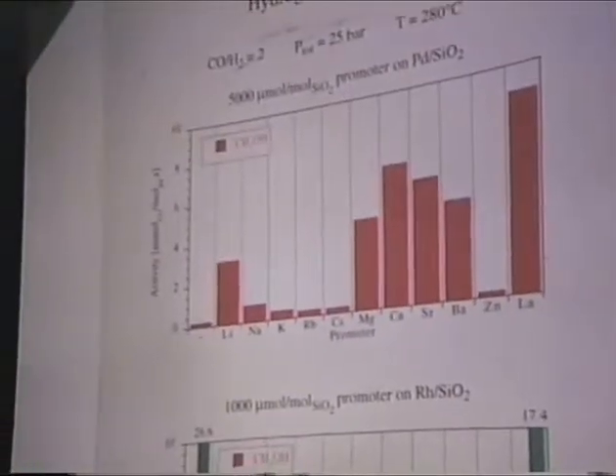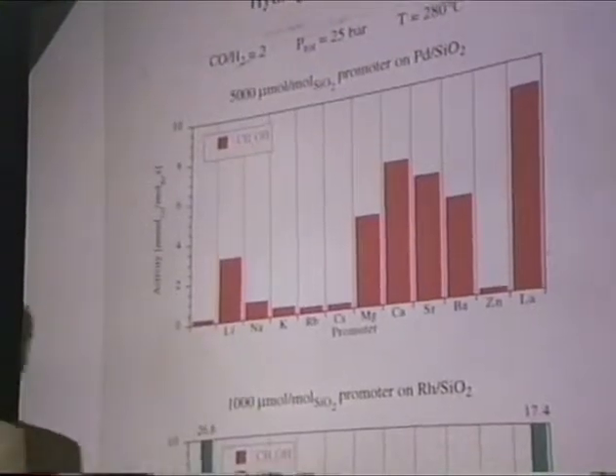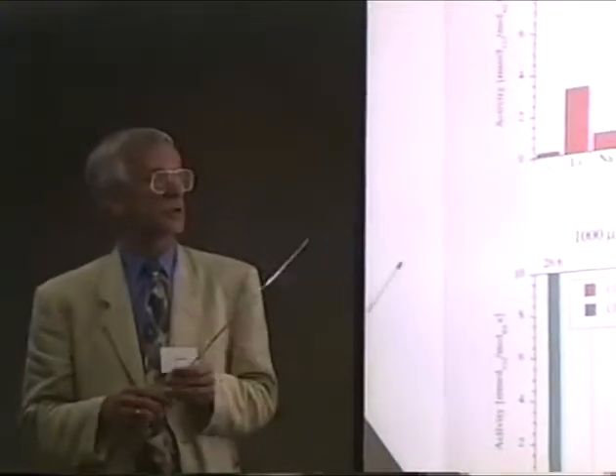If we assume that these promoters must be close or on top of the metal, you must ask yourself the question, how do they come there? How do we prepare our catalyst? The answer is, we make a palladium on silica catalyst and we impregnate it with a solution containing the nitrate of one of these salts. And then the question is, does it really reach the metal?